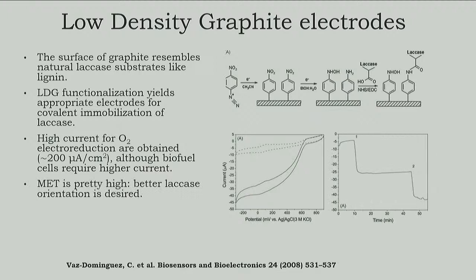But what happens if we put a mediator? This is a molecule that is going to shuttle the electrons from the enzyme to the surface. In this case, we can see the enzymes that are not properly oriented, because we can try to convince the enzyme to be in a good orientation, but there will always be some portion of enzymes that are not oriented well. Here we can see direct electron transfer, where we get this increase in the negative current, and when we put in the mediator, we can see that more or less half of the enzymes are not properly oriented. Okay, this work was from 2008, and in the next 5 to 10 years we have been improving it. But this was, for me, the beginning of this very interesting work.